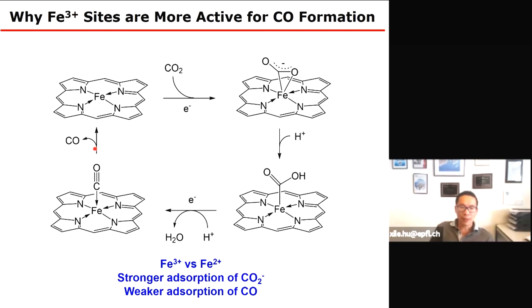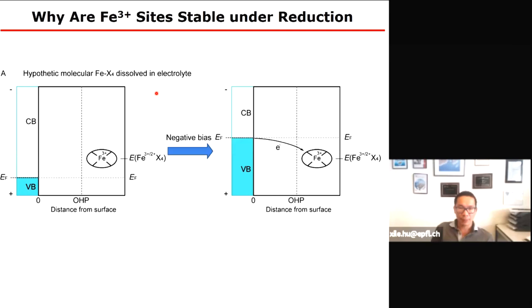In fact, we also find that even for the first step, the CO2 absorption, the iron 3 site is more advantageous than the iron 2 site, and that can explain why it's more active. Now, the real puzzle is, why do we have stable iron 3 sites at reductive potential? And this involves a new mode of cooperative catalysis.